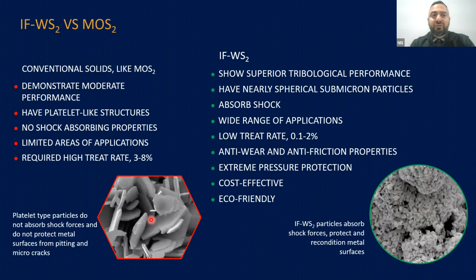Because regular molybdenum disulfide or tungsten disulfide particles are flat, they usually transfer the load and shock to the metal, creating micro-pitting, micro-cracks, and all of the negative outcomes of the shock, specifically in gear applications. Also, because they're flat and quite large, the loading is usually between 3 and 8% in a fully formulated product. We can do the same with a fraction of that. Usually, the treat rate of tungsten disulfide spherical particles is between 0.1 and 2%, depending on the application. It's more eco-friendly, more cost-effective. It has really good extreme pressure protection because of the spherical geometry. And it has a very wide range of applications.